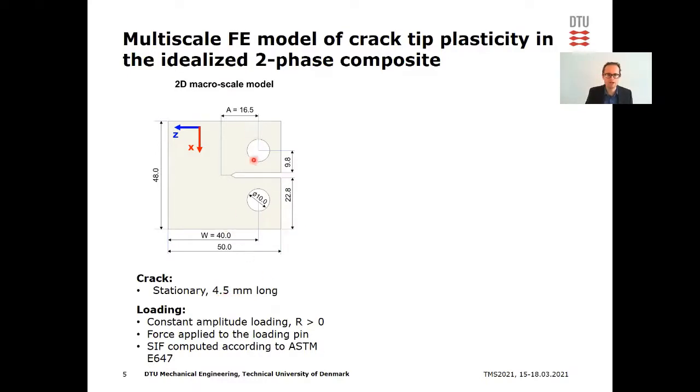And we load this model by applying a time-dependent force to the loading pin in order to recreate a situation of constant amplitude loading with a positive fatigue ratio. And at any time, for any value of the force applied to the loading pin, we determine the stress intensity factor at the crack tip by applying just standard formulas.